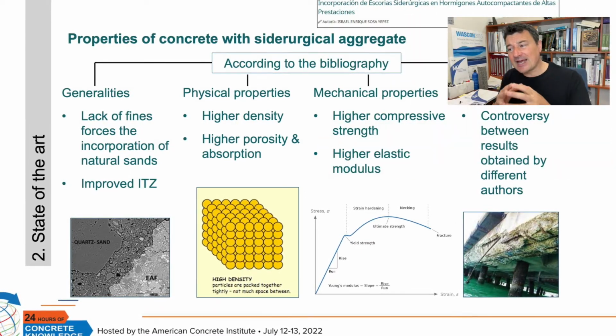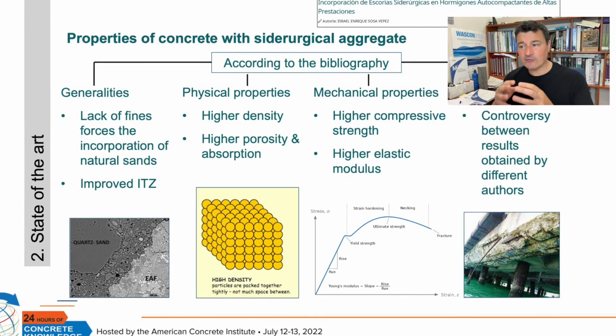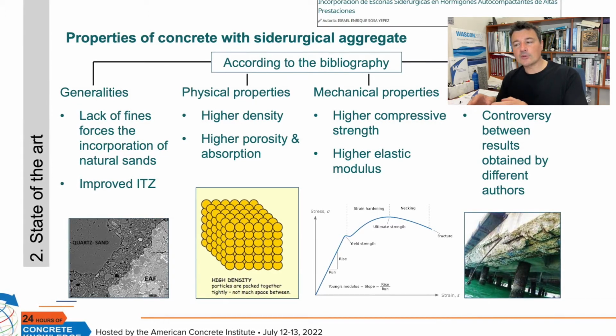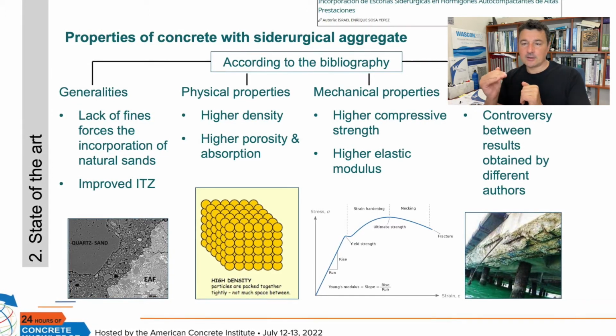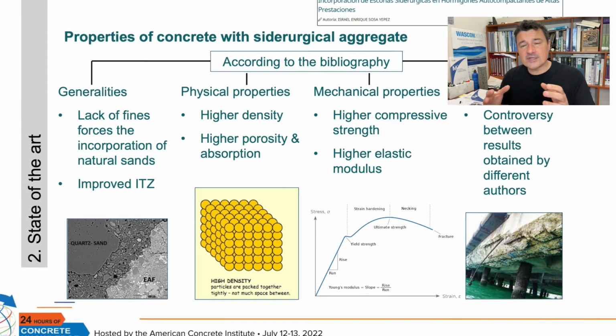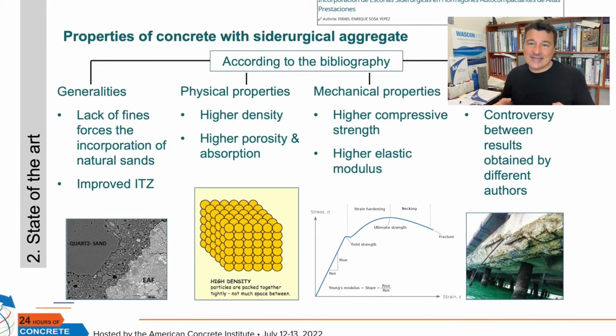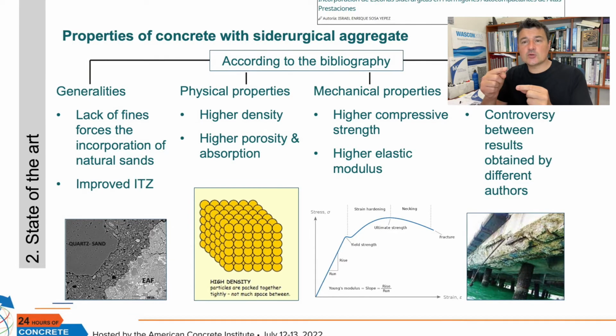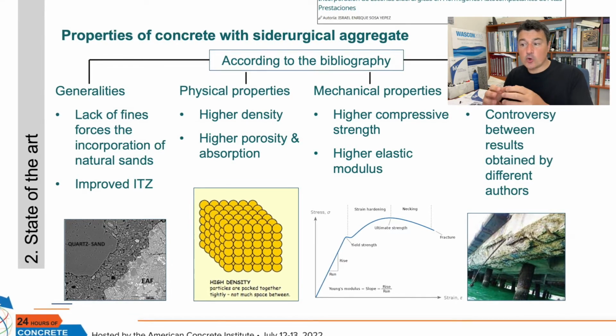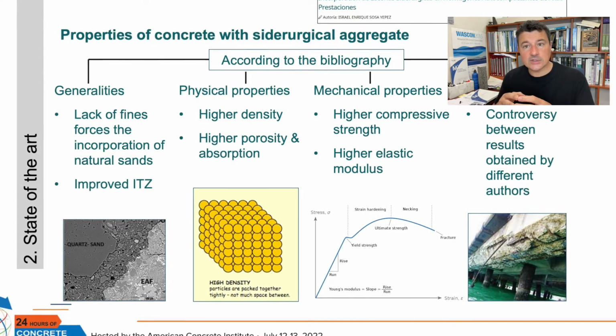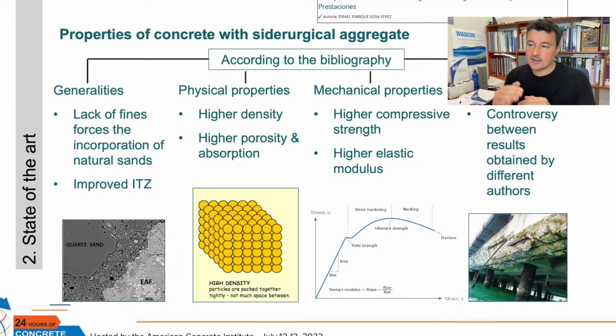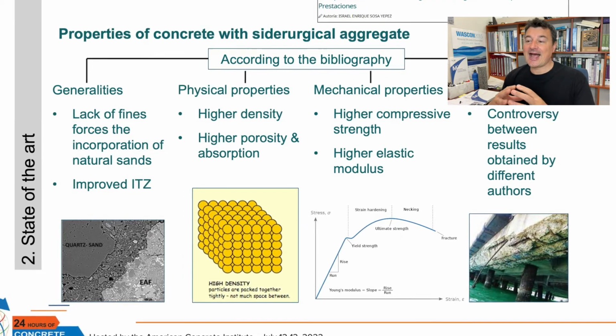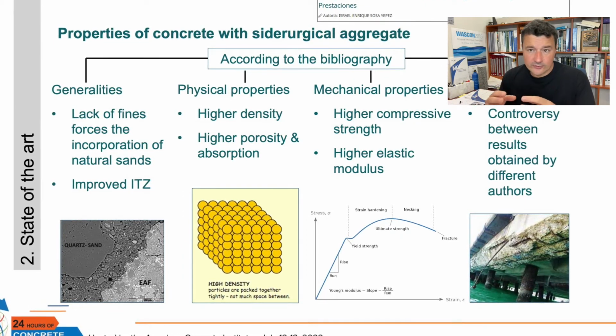But the mechanical properties of the concrete performed with siderurgical aggregate are much higher than the compressive strength, for example, of the standard concrete using natural aggregates. Also, the elastic modulus, the Young modulus, is higher in this case because the higher elastic modulus of the aggregates.